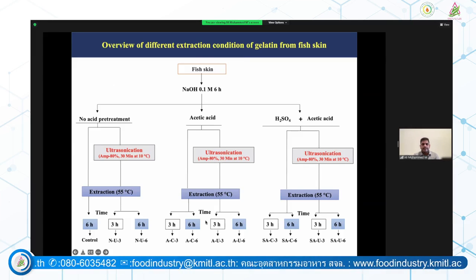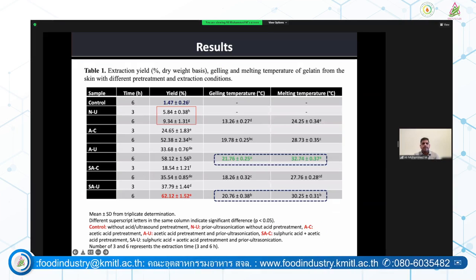We used the extraction conditions at two time intervals, 3 hours and 6 hours. Six hours is the ideal condition, and we are trying to check whether, with the help of ultrasound, 3 hours will be feasible when compared to the conventional method. Here we can see the extraction yield, and this is the control with 1% yield of fish skin. This is a very low, negligible extracted yield. With ultrasound, without any acid treatment, the extraction yield has increased to up to 10%. And with the aid of different acids, such as acetic acid and sulfuric acid, the extraction yield in combination with ultrasound has reached 62%. This is very significantly higher.